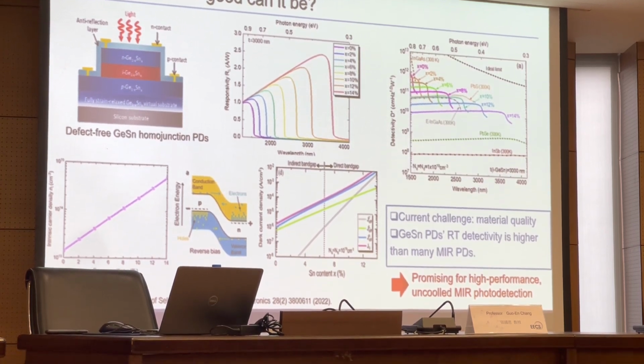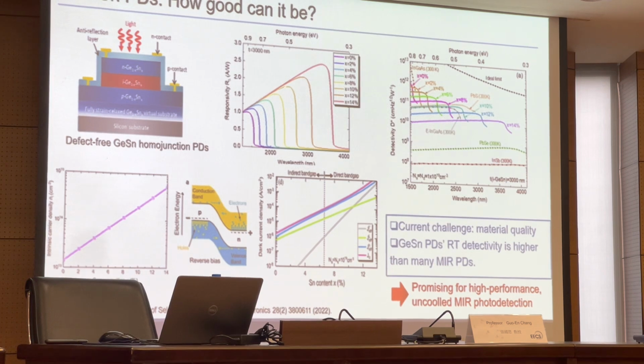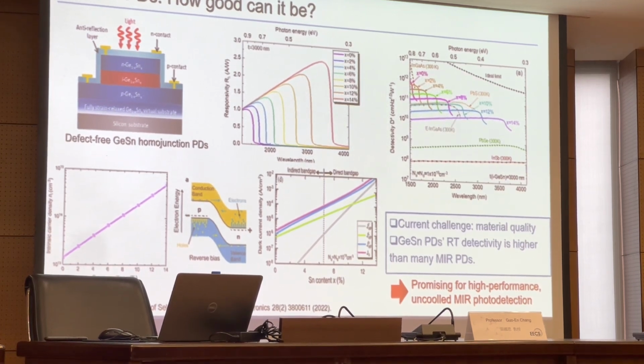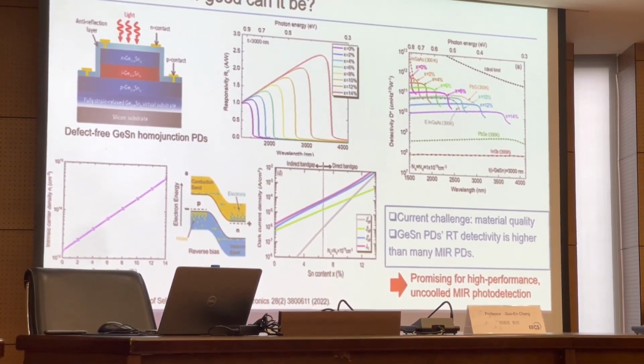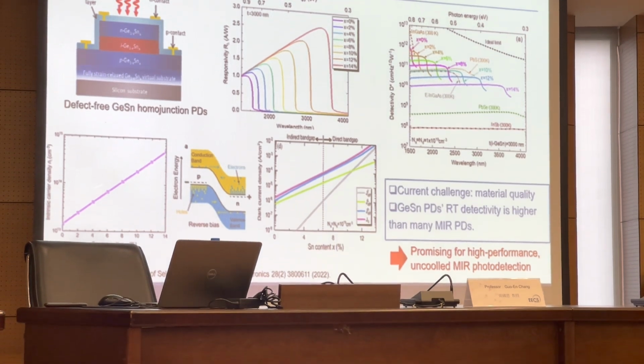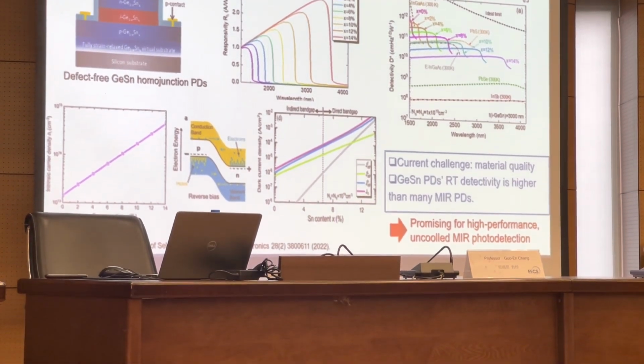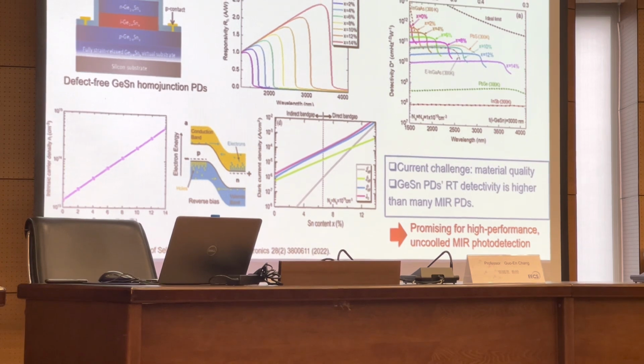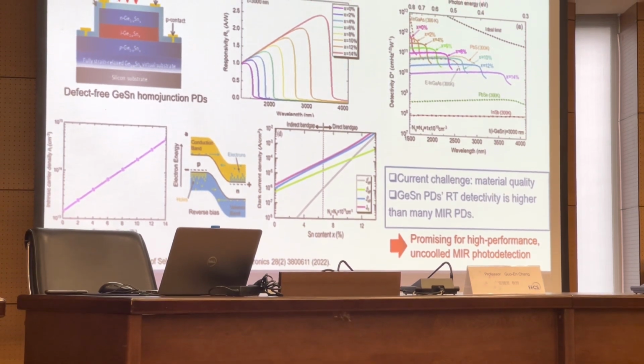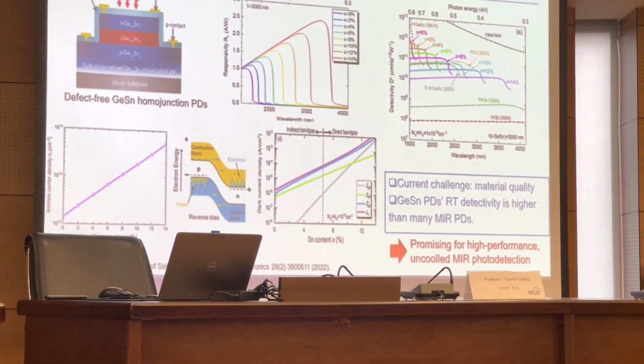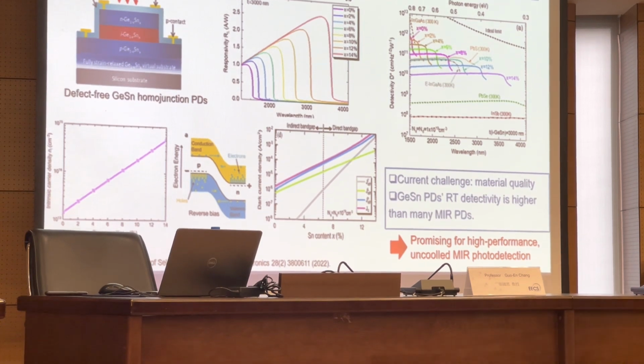At the same time, the responsivity value also increases. When we increase the tin content, the bandgap energy becomes smaller, so the intrinsic carrier density in the conduction band and valence band will increase as well.